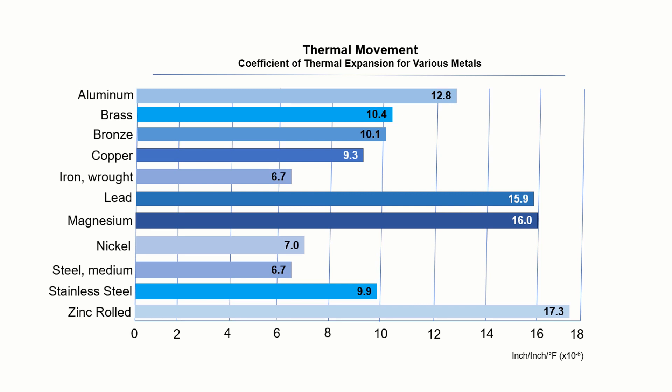You have aluminum zinc-coated steel, often referred to as zinc-alume or galvalume, and then pure aluminum. As a rule, coated steel will expand and contract at about plus or minus an eighth of an inch per 10 feet of panel run. For 40-foot panels, that's about half an inch or more. Long roof runs can expand and contract at upwards of one inch or more when panel lengths get into the 80-foot range. By comparison, aluminum has twice the rate of thermal movement as steel — for the same 40-foot roof, aluminum would expand and contract about one inch.